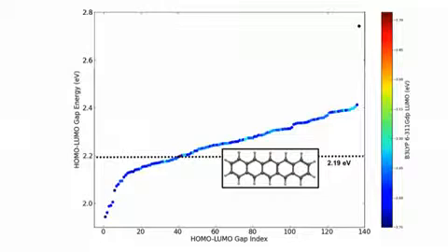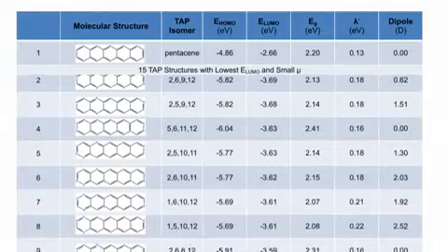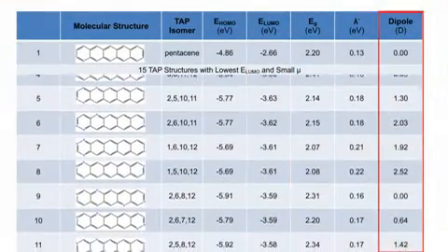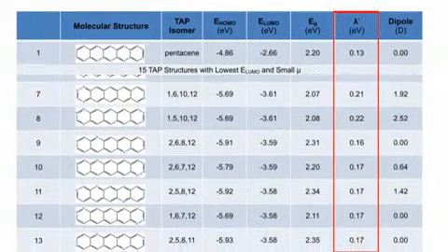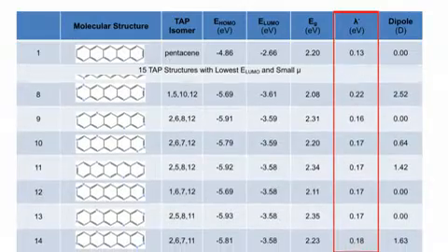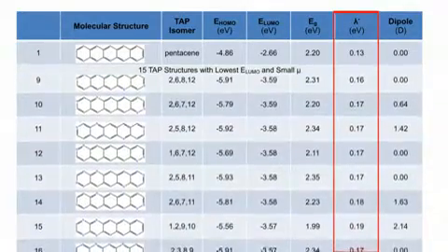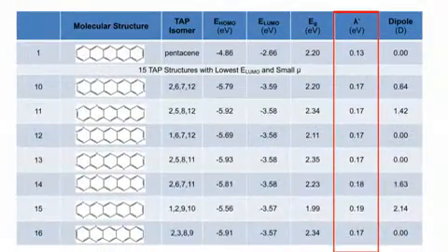Here, the HOMO-LUMO gap energies are shown and compared to C60 are predicted to have lower and therefore more favorable gap energies, which should satisfy a partial requirement for enhanced optical absorption. 15 exemplary tetraazapentacenes are shown here, which have the lowest LUMO energies and low dipole moments, and all of which have computed electron transport reorganization energies less than 0.25 eV and comparable to that of pentacene, suggesting that these structures should show efficient electron mobility when good electron coupling in the condensed phase is achieved.